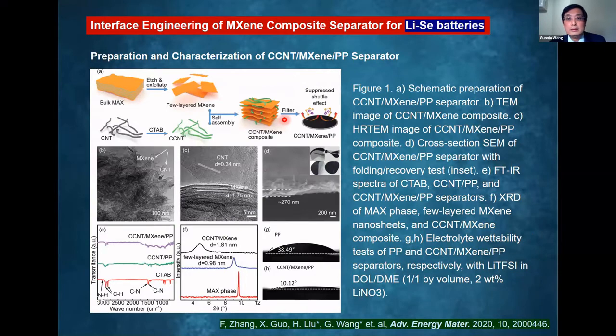And recently, we also extended another application of MXene. In this case, we coated MXene nanosheets on the commercial separator for lithium selenide batteries. So here you can see the contact angle. When you coat MXene on the PP separator, you can see the contact angle becomes smaller.